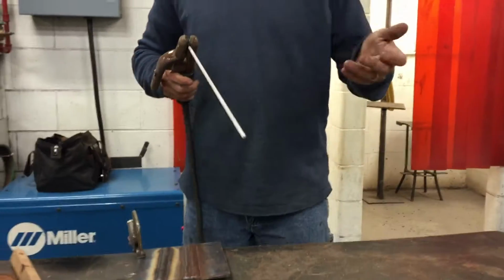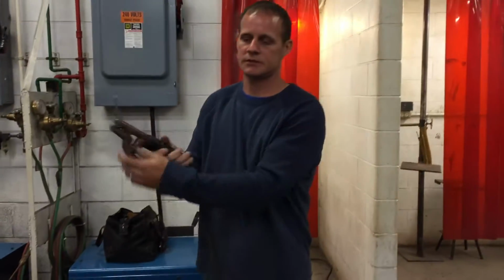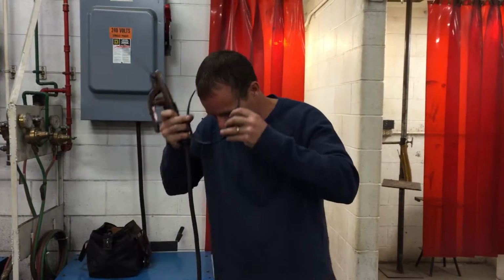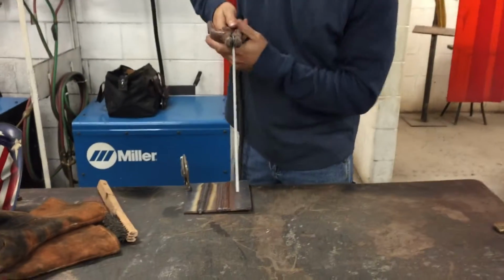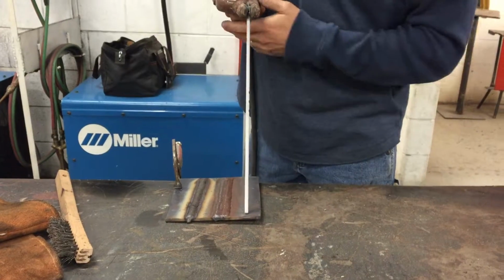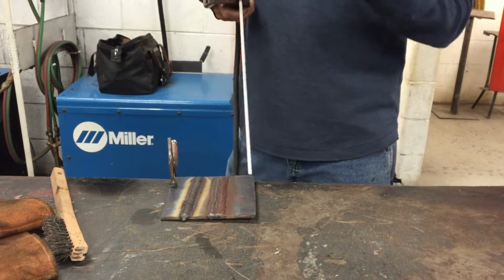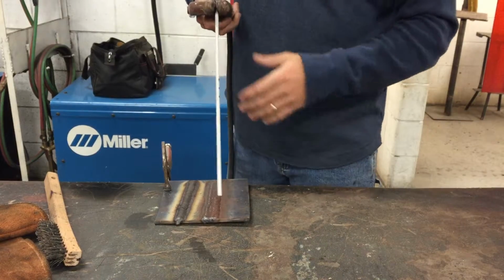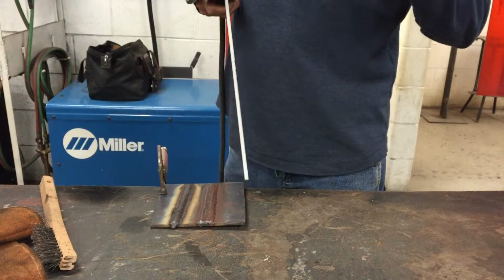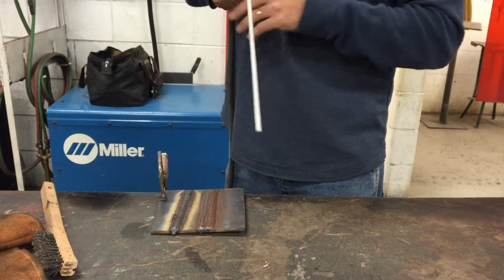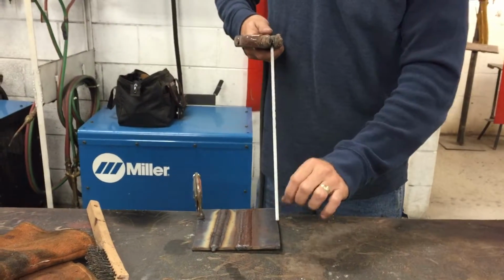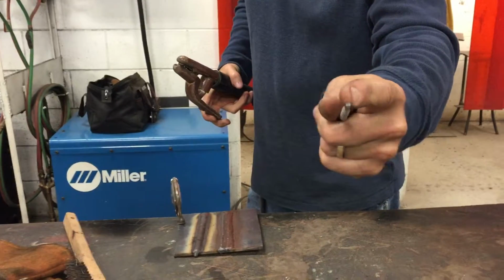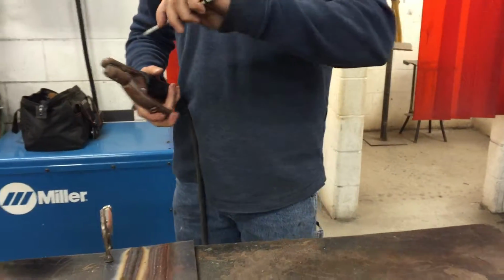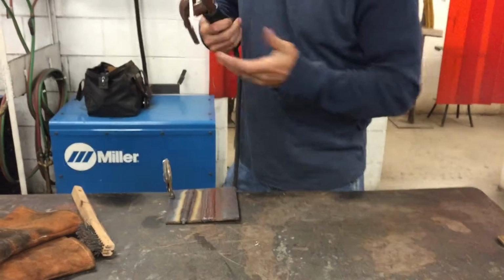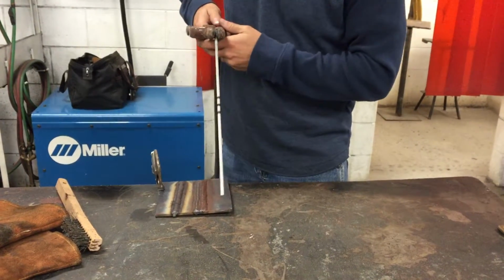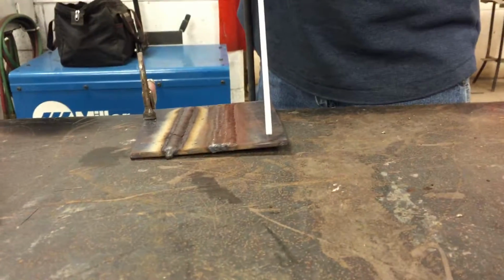Now, there are different theories and different practices on this. I'm going to put my safety glasses back on for this next thing. A lot of people want to touch the welding rod to the metal and make the weld that way. If you do that, I suggest you run a little higher heat. Technically, our RT Miller Weld Skills book suggests that we run an arc gap the diameter of the welding rod, which is 1/8 of an inch. I run about 1/16 to 1/8. Stabilize yourself, and then you run your weld down through there.